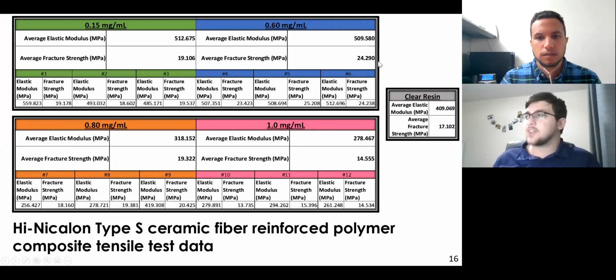Additionally, the 0.6 had a higher average fracture strength, which is another reason that we ended up using this concentration instead. And then you can also see that the 0.8 and the 1.0 even underperformed compared to a neat resin. That was pretty consistent in each of their samples, with the exception of sample 9 here, which had an elastic modulus closer to the neat resin.